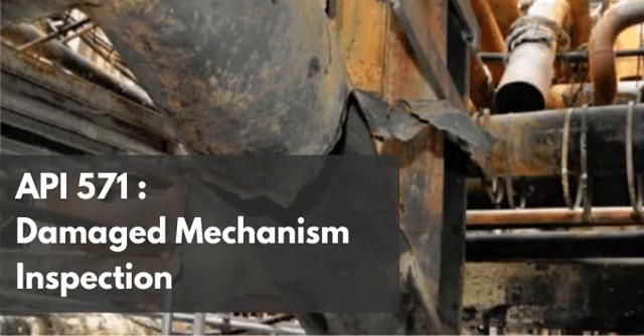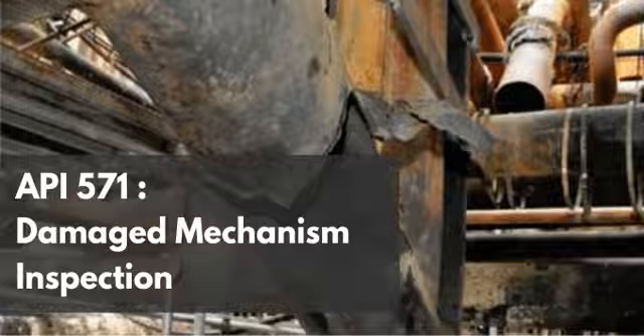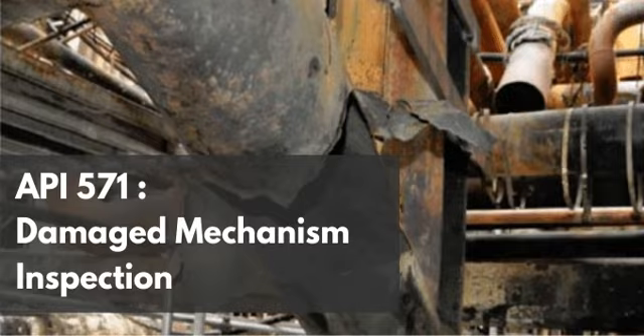Okay, so we know the underlying physics, we know the fluid dynamics, and we know exactly where these cracks will form. The challenge now falls to the field inspector. This is where the rubber meets the road. Exactly. Section 5. In situ inspection and damage detection. The refinery is running, the equipment is covered in decades of operational scale, and you have a potential network of microscopic, oxide-filled grain boundary cracks hiding 1/10 of an inch from a nozzle weld. Good luck seeing that with the naked eye.